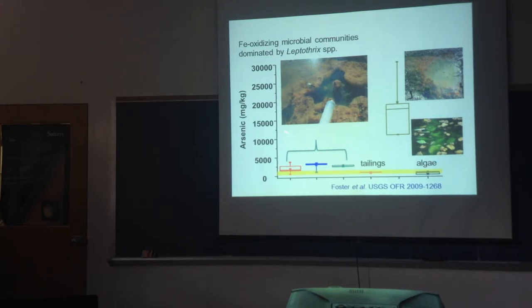But in this environment, we got several thousand. And then there was one series of samples that were these very floc-rich materials that were actually in the 10,000 to 20,000 range. So actually up in the 1 to 2% arsenic in some of this material. It was very fine-grained, and it does a nice job. Iron is actually very effective at absorbing arsenic.